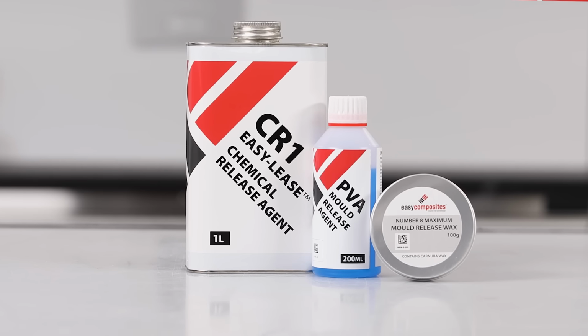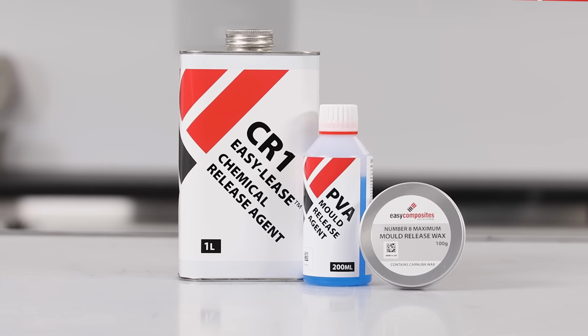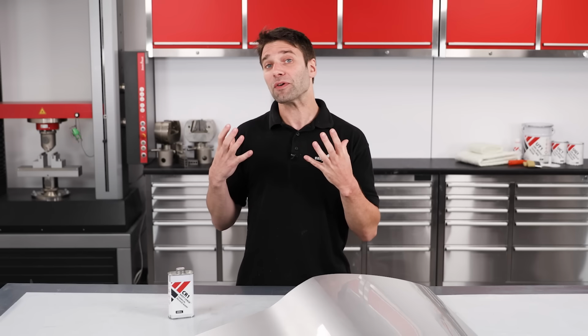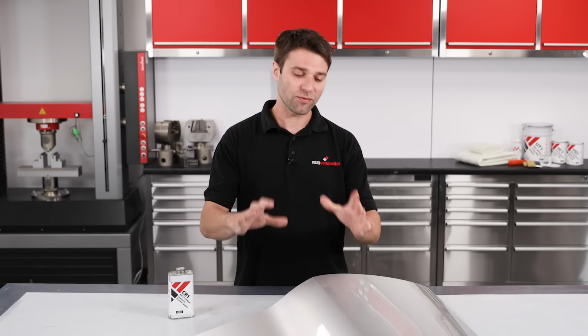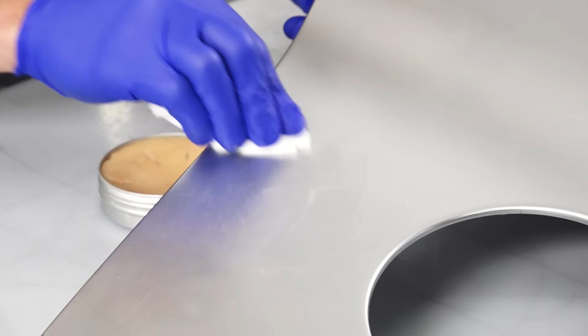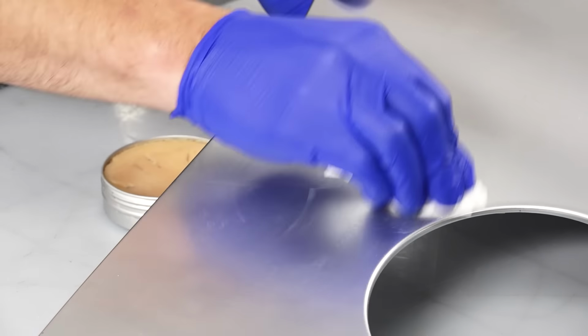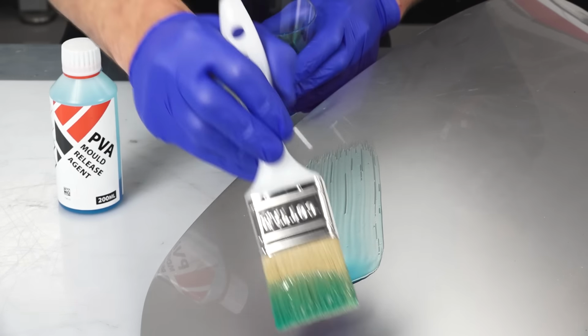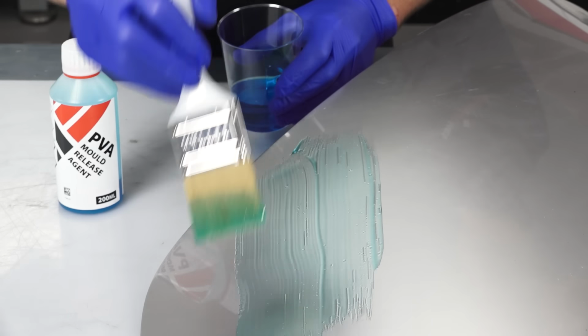So that's liquid wax, paste wax, PVA or chemical release agent. If you have a preferred method that works well for you, feel free to stick with it when you're working with the Uni-Mould. Wax does produce excellent surfaces and reliable releases, but it does take time to apply and relies on good application technique. PVA is really useful for quick, reliable releases on lower quality patterns, but it's not going to leave an A-class finish, and so you might need to sand and polish your mould if you do need that quality finish.